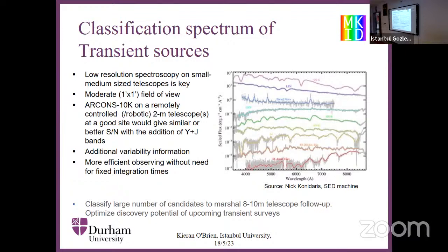In fact, the same MKID is sensitive to light all the way from 400 nanometers up to 2 microns. So you can use the entire bandwidth. There may be reasons you don't want to. By the time you get into the infrared, you have additional issues like the sky brightness, which has more photons, but it certainly doesn't stop at 1 micron.